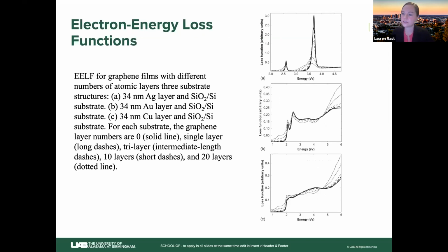For a few layers of graphene, the lower peak, which is near about 2.6 eV, is virtually unchanged. On top there, that's for silver as an intermediate layer, and then a silicon dioxide substrate. So we go from zero layers of graphene, the solid line, then a single layer with long dashes, then 3 layers for the intermediate length dashes, then up to 10 layers for the short dashes, and the dotted line corresponds to 20 layers of graphene.